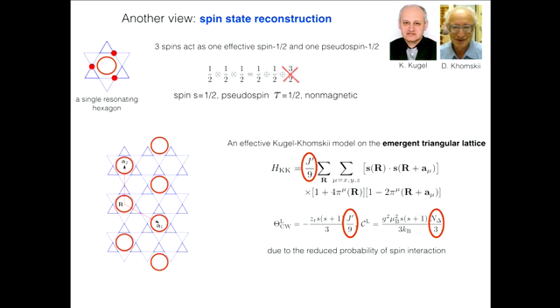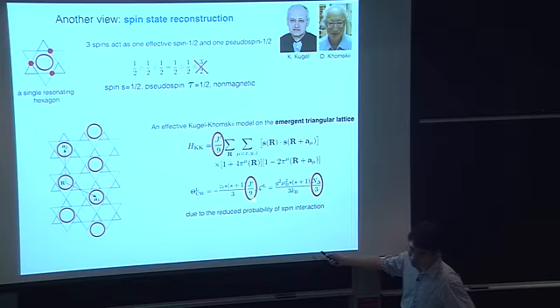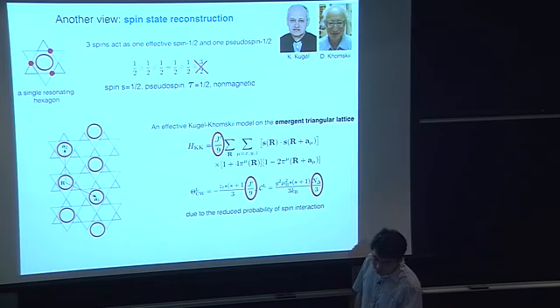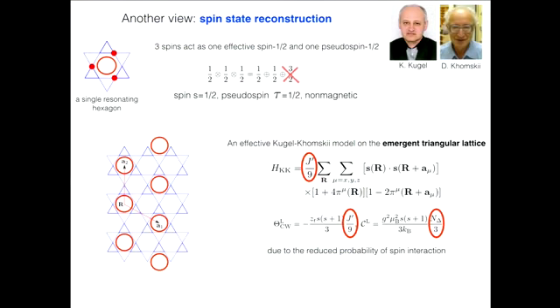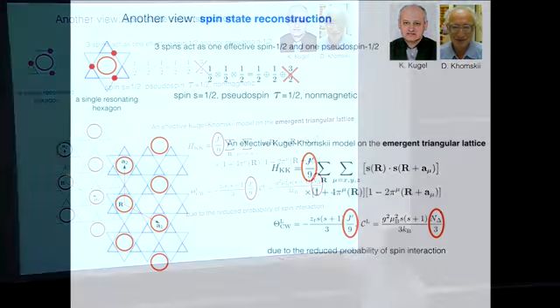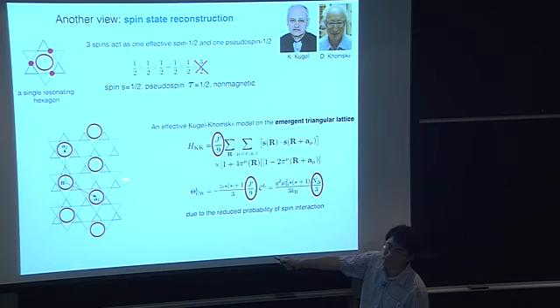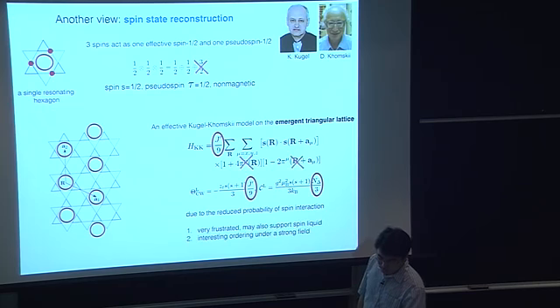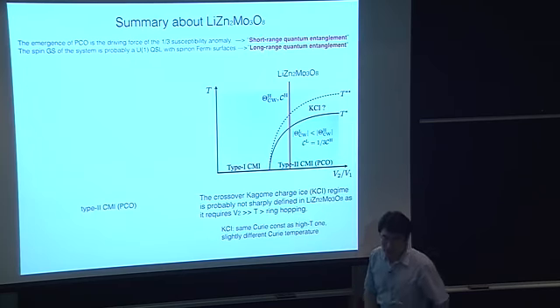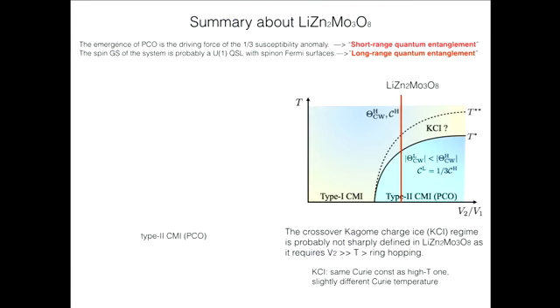In fact, we can compute this Curie-Weiss temperature, and the reduction by a factor of 9 here. This reduction is due to the reduced probability of spin interaction, because originally each spin can interact with its neighbors, but after they form this superposition state, the probability to have this interaction is reduced. So I want to give a summary on this material.